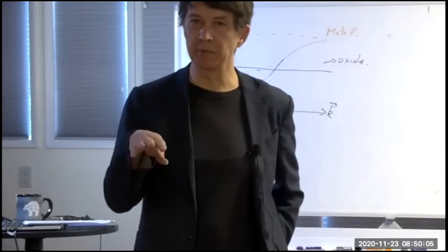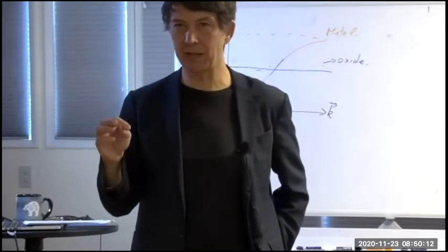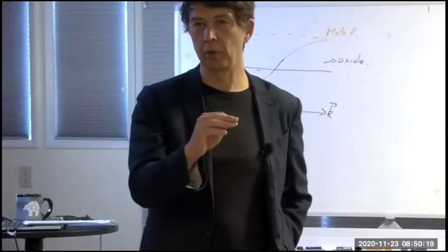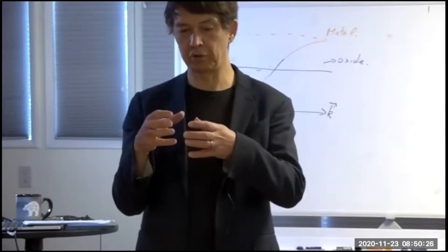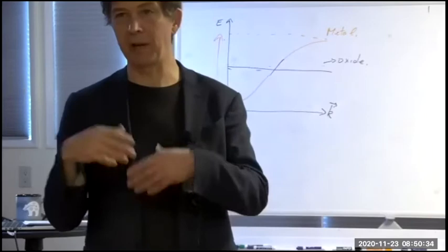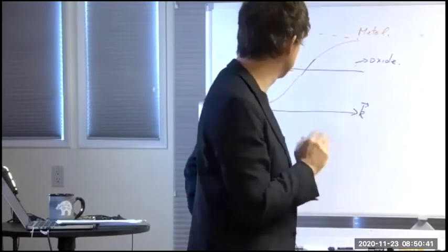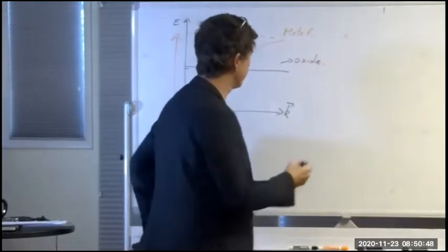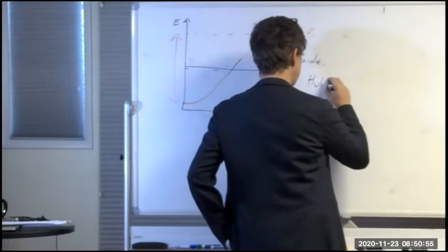If the tunneling rate becomes extremely slow, let's take some extreme. Let's say the tunneling rate is a second on average, so it takes a second on average before an electron tunnels from one atom to the next. At that point, the electron localizes, because the electron sits on an ion, and the structure has more than enough time to relax around it, right? It feels an electron and adjusts its size, because if I have an electron, I'm bigger. And so you get what's called a polaron. You get trapping of the electron. So at that point, the band picture is completely gone. You get localized states, right? And this is sometimes what's called, the word you want to remember if you talk to Professor Ramesh by accident on your qualifier, things like Hubbard localization.